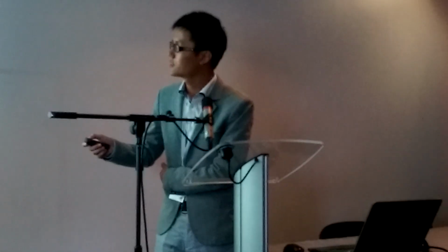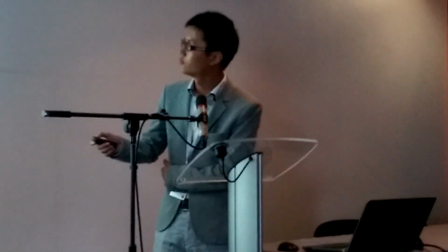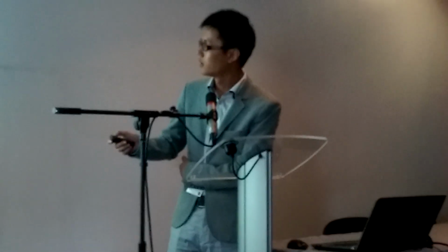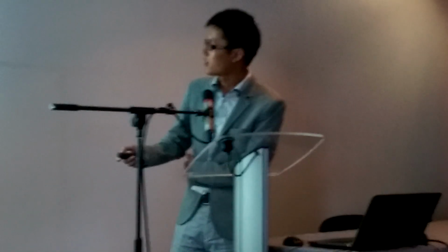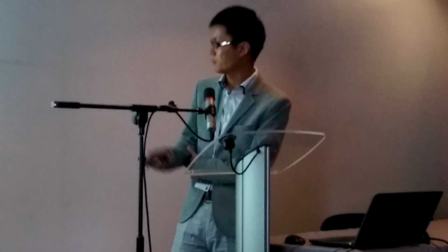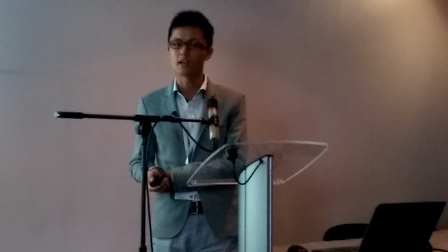And we can see that the peak of iron monosilicide, 211, was decreasing along with the increase of the ambient pressure, which indicates that the content of iron monosilicide decreased at higher pressure.